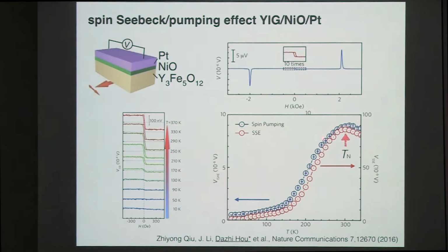But if you look at the temperature dependence of the inverse spin Hall effect, you will find that at very low temperature, the spin transmission of this antiferromagnetic system becomes nearly zero, which means the rational expectation for the SMR at low temperature should be zero, right? You don't have any spin transmission across it, which means the platinum cannot really feel there is YIG beneath this nickel oxide. So basically, here we should expect a zero SMR, right?